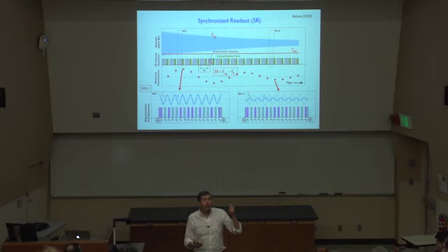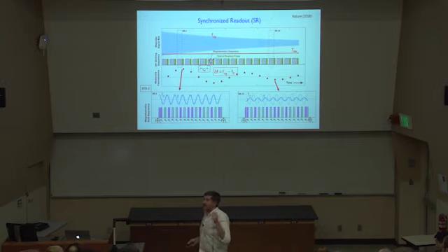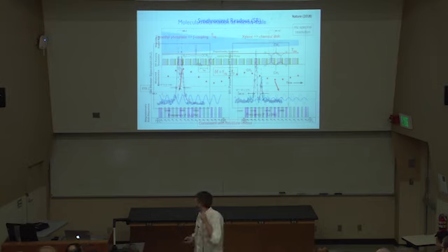If you have an even more coherent signal, like something you create from an antenna with longer coherence time, you can just average and average and average and take longer sequences, and that's where we went out to a little better than a millihertz. That's like 1,000 seconds or more, and then you get tired and stop doing it. But you could have kept going, right? So this is a wonderful, simple idea. It's easy to implement. All it means is just implement a different pulse sequence and lock it and have everything controlled with a clock and synchronized.